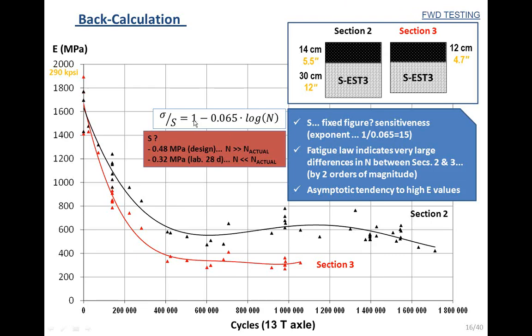According to this formulation, when we compute the stress at this point and the stress at this point, we were expecting a very large difference between this section and this section. As I wrote here, fatigue law indicates very large differences in N, the useful life. We were expecting very big differences between sections 2 and 3, in particular 2 orders of magnitude. In this formula, the exponent of the stress is 15. Very small differences in stress mean a very large difference in fatigue life. S would be the tensile strength of the material.